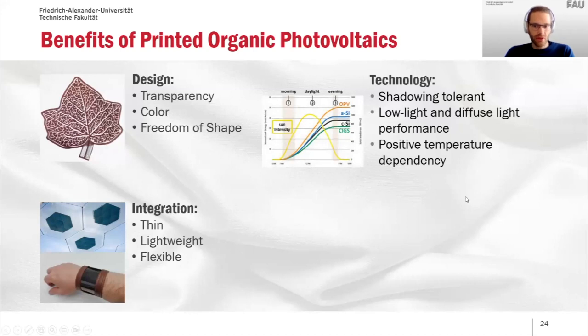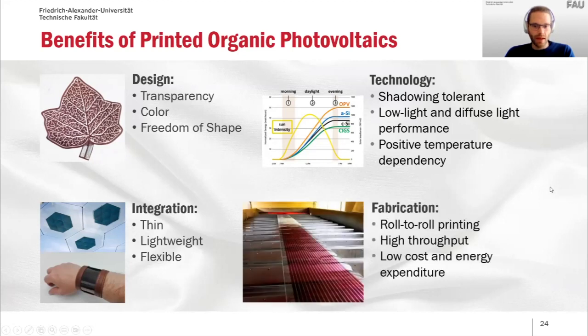They have some technology advantages, which I won't go into detail, but for example, they have a positive temperature dependency, which means that in contrast to silicon modules, which actually get a lower performance if they heat up during the summer at noontime, they actually remain their efficiency or even get a little bit better when they get hot. And a very important benefit is that you can manufacture them in a roll-to-roll printing process, which means with a high throughput and at low cost and energy expenditure.